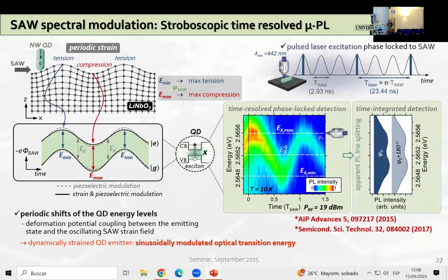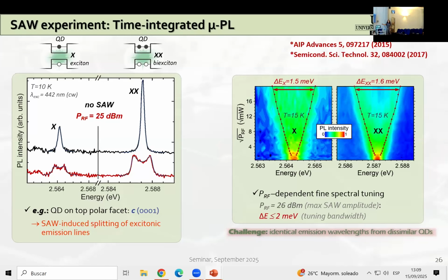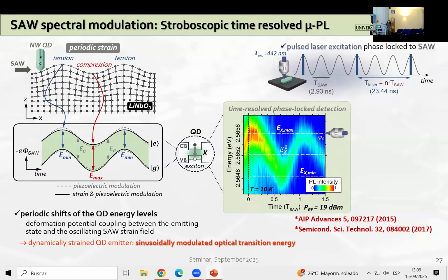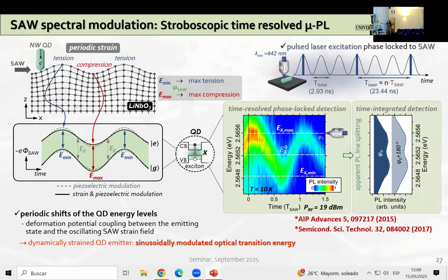So you can see here, this is the time resolved measurement. If you would do it without the acoustic wave, you would just see the exponential decay, let's say mono-exponential decay of an exciton or bi-exciton complex. But when you apply the acoustic wave, then during this decay, what you see is that the transition energy is really modulating sinusoidally, because the signal that we apply to the IDT has a sinusoidal form, right? So then what I showed here, this splitting of the line, is actually what we obtained when we integrate this over time, and then we get this apparent splitting. So what actually happens is that during the decay, when acoustic wave is applied, the strain or the deformation potential coupling is what causes this modulation of the optical transition energy. So it oscillates sinusoidally like this.